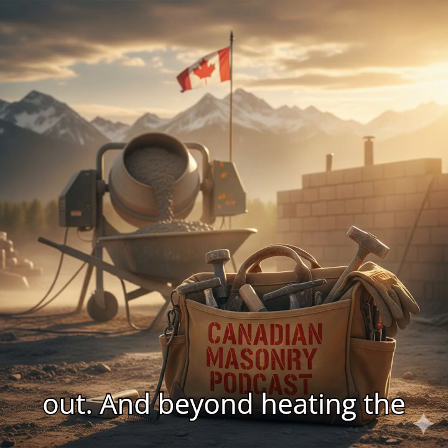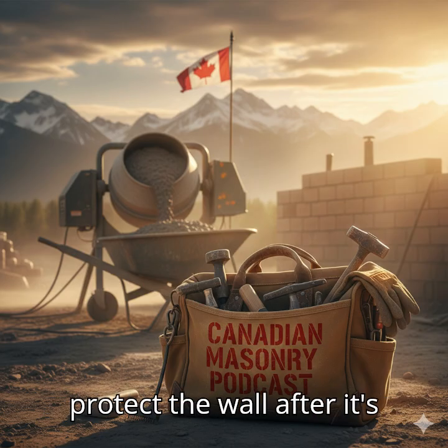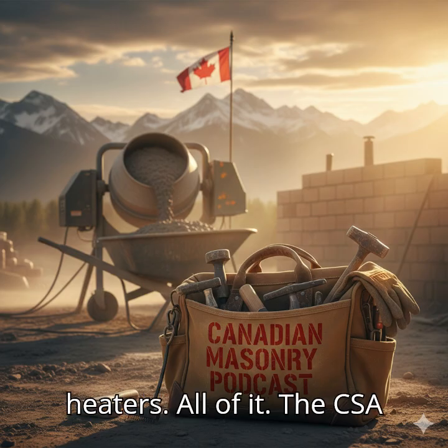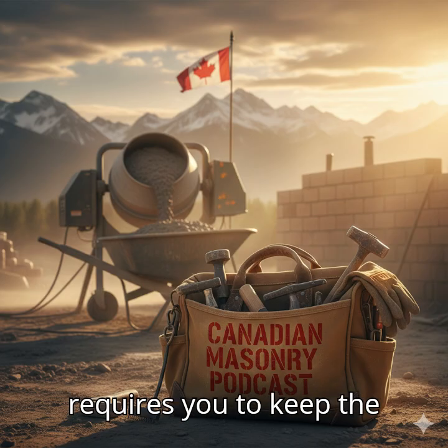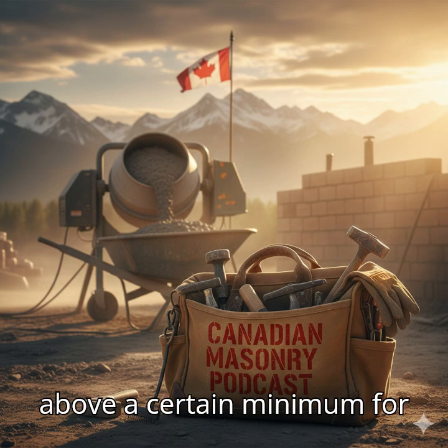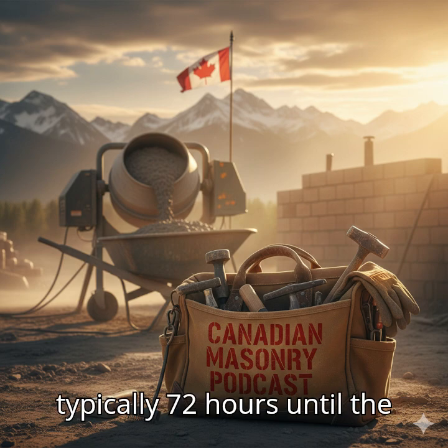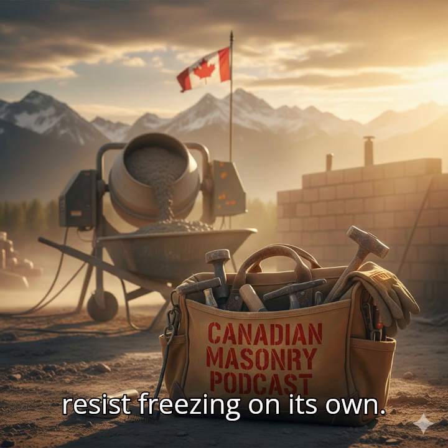Yeah. And beyond heating the materials, you have to protect the wall after it's built. Tarps, enclosures, heaters. All of it. The CSA requires you to keep the temperature of the masonry above a certain minimum for typically 72 hours until the mortar is strong enough to resist freezing on its own.